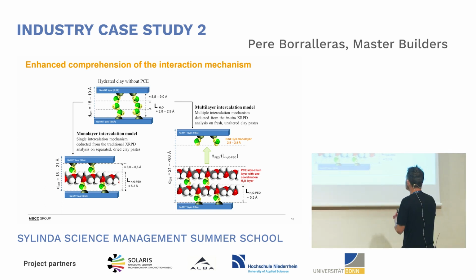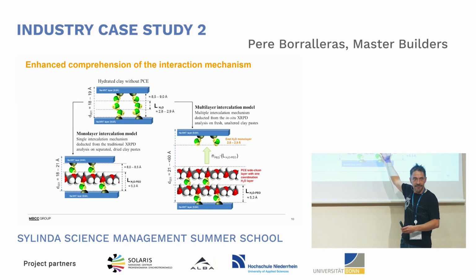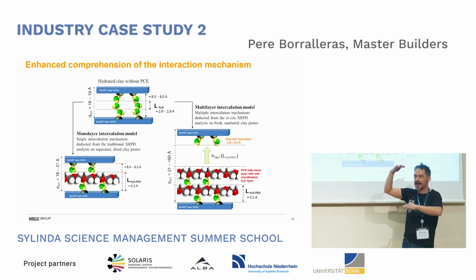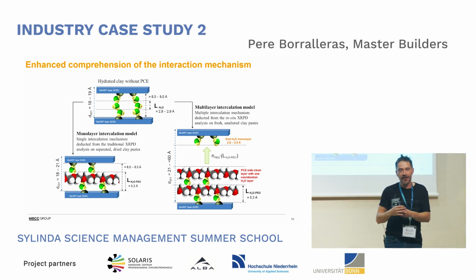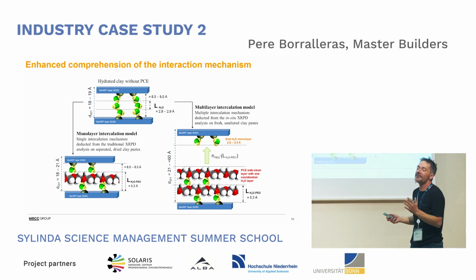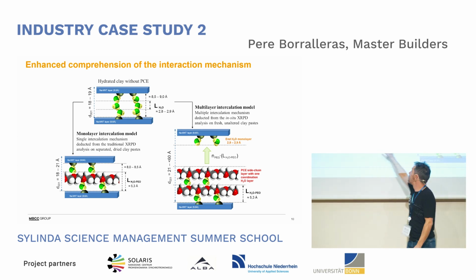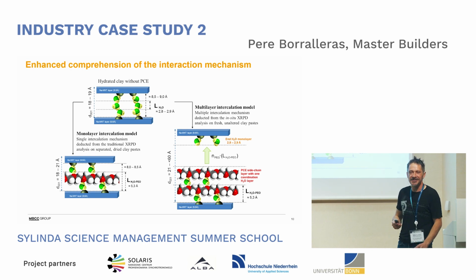Just measuring the distance and knowing all this information, we see that even up to 8 ethylene side chains were intercalated in the clay, so it means much larger expansion than assumed by just one layer, the monolayer model. Okay, that was like taking off the blindfold. You know, but opening the eyes again at least. But definitely, if we have to design admixtures in order to overcome one problem, all the things that we were doing, assuming this model, were not performing, but assuming this, well, then the picture dramatically changed.